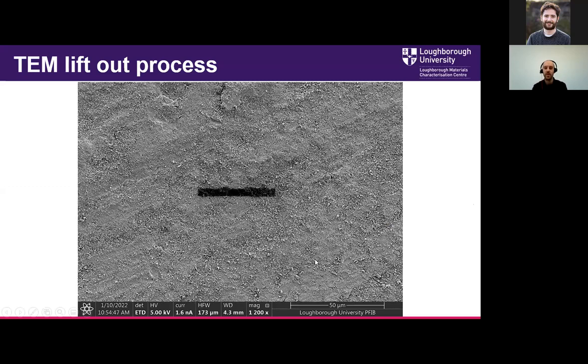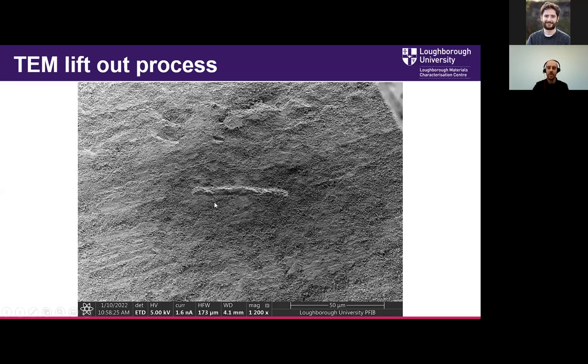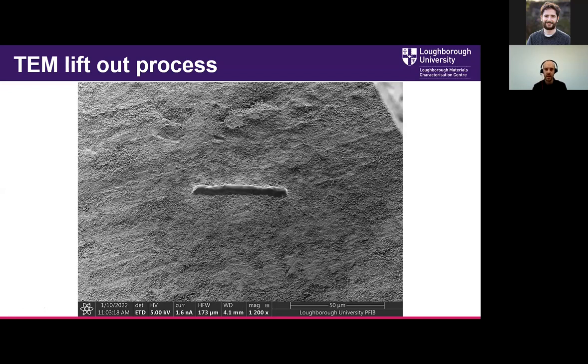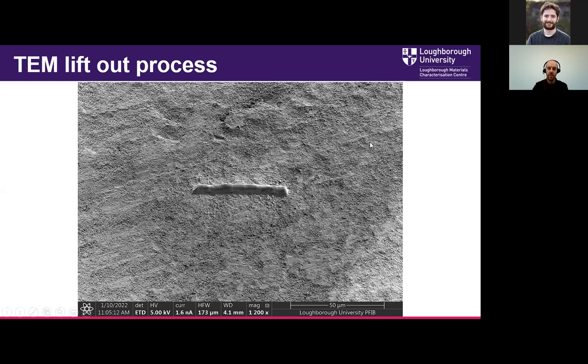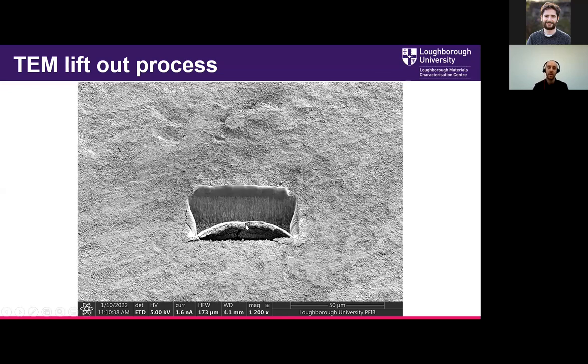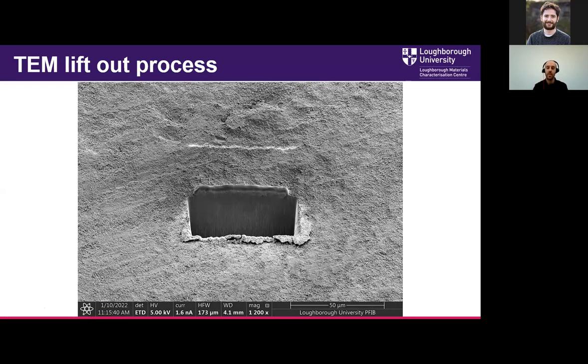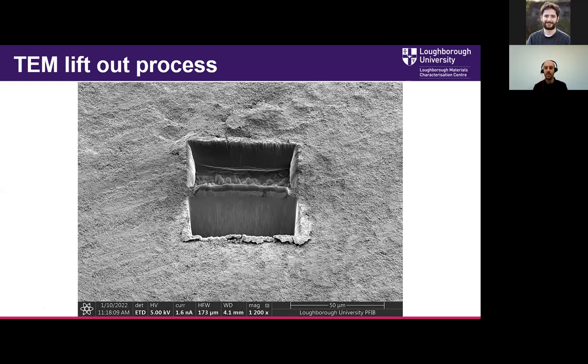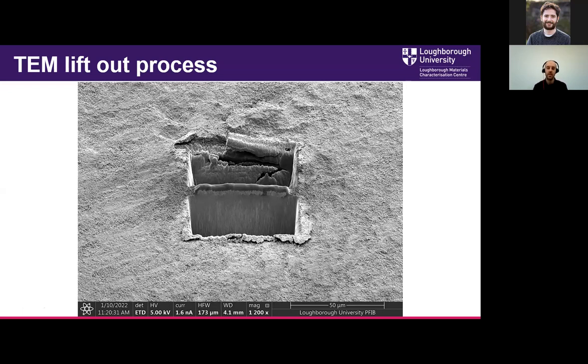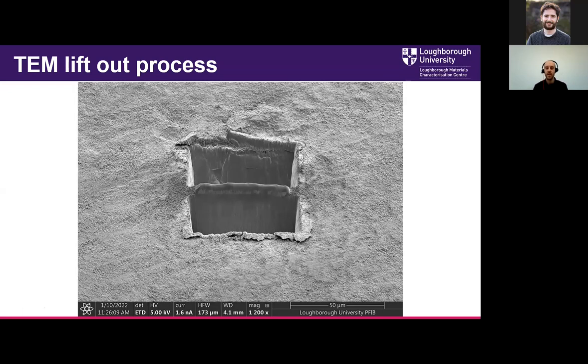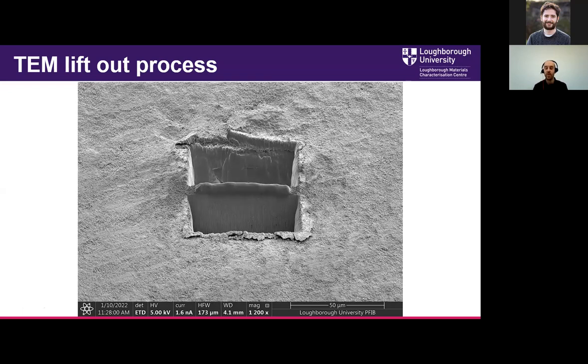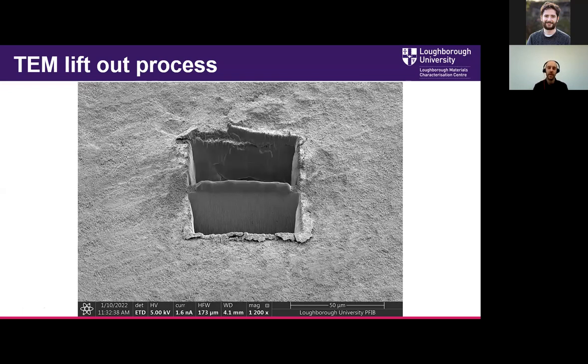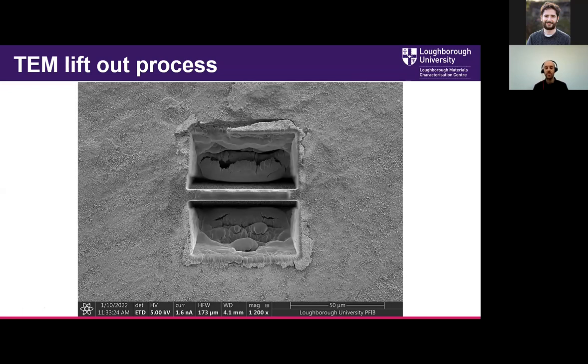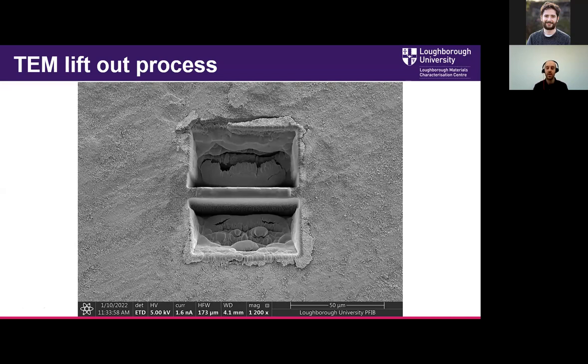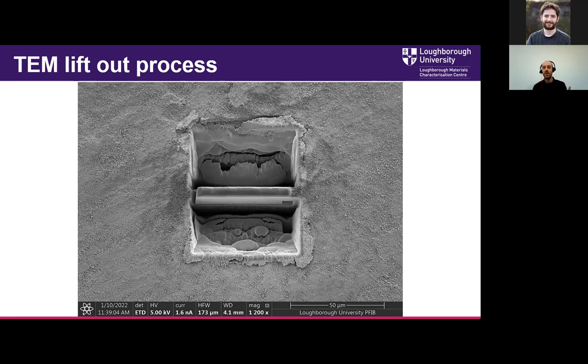So here's an example of how we might do a TEM lift out. First we deposit some electron beam platinum, and then we deposit some ion beam platinum or tungsten in this case. You can see the GIS needle in the top right corner, and then you can see we would do a staircase cut to make a lamella that is still attached to the bulk. So this is cutting at high current either side. And then we would tilt the sample slightly, and we would use a lower current to polish the surface. And then once we've done that on both sides, we could drop back down to 0 degrees and undercut the sample. So it's just held on by a little edge.